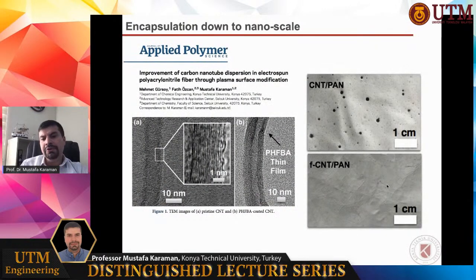We use chemical vapor deposition to encapsulate powder substrates in the rotating bed PECVD system that I showed you previously. Usually, such particulate materials are used as fillers in a polymer matrix to make polymer nanocomposites. The major problem in the synthesis of polymer nanocomposites is that such fillers are not dispersed efficiently in the matrix. They tend to agglomerate because of the poor interaction between the matrix and the particle surface. If we apply a very thin layer of CVD coating on the particle surface, we have the power of improving the interaction between the matrix and the material.